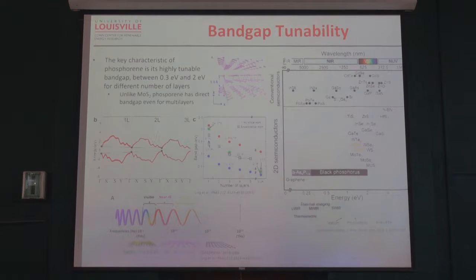So this is the important thing. If you take phosphorene, you can see going from 3 layers, 2 layers to 1 layer, your band gap is changing. Here you have 3 layers, you have this small band gap, and it's becoming a little bit bigger. If you go to 1 layer, that becomes almost 2 electron volts. So with the number of layers, you can change your band gap dramatically for phosphorene.